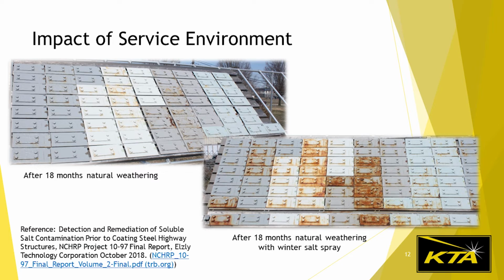So basically what works in one area of the country is not going to work in another with a harsh environment. So soluble salt testing and remediation are vital for a successful project in these environments. And one thing to consider when testing for salts, there tends to be higher levels in the pitted areas or areas of high corrosion. So your inspectors should be performing salt testing in those areas.